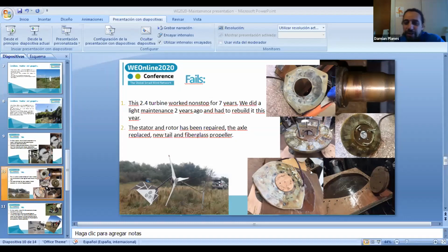Jonathan, I had this turbine, exactly as you see, with that problem. The rust was going inside, under the resin and into the magnet. In this case, I painted the whole disc. What I saw in a lot of turbines is that when you don't paint the whole disc, the humidity goes through the disc below the resin and rusts the magnets. So it's very important to paint the whole disc, to not let humidity enter below the resin. And for EO local, for example, we galvanized the complete disc. So it works much better.